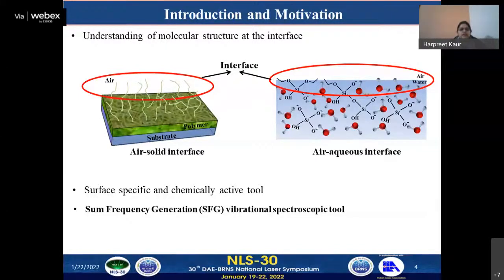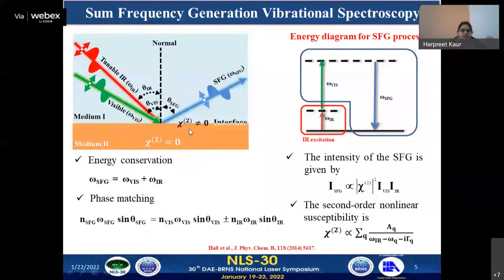It is a second order nonlinear process in which two fundamental laser beams are overlapped at the interface, where chi2 is not zero due to the non-centrosymmetric environment of the molecules at the interface. For SFG to occur, two fundamental laws of physics should be followed: one is energy conservation and another is the phase matching condition. Depending upon this phase matching condition, one can detect the direction of the SFG beam. The intensity of this SFG beam is enhanced resonantly when the frequency of the tunable IR matches the resonant frequency of the interfacial molecules. So the SFG spectrum is obtained as a function of frequency of the tunable IR, which is upshifted in the visible region of the electromagnetic spectrum.